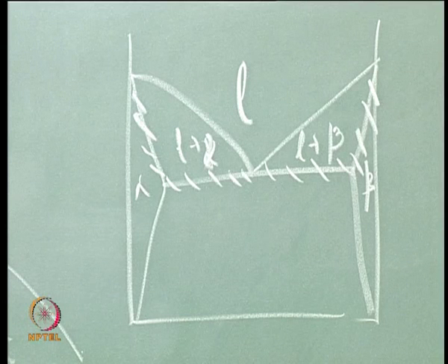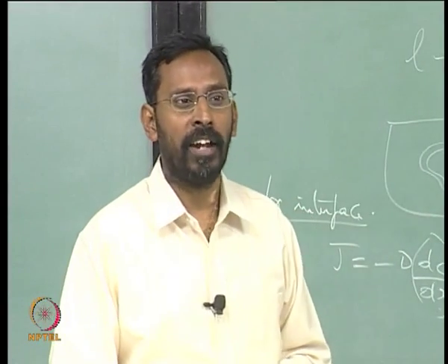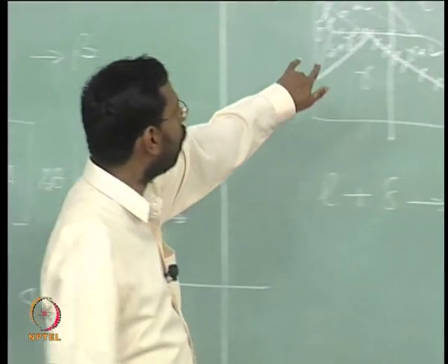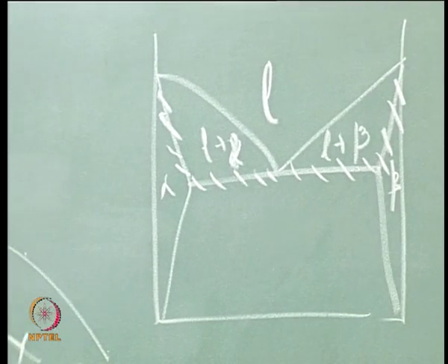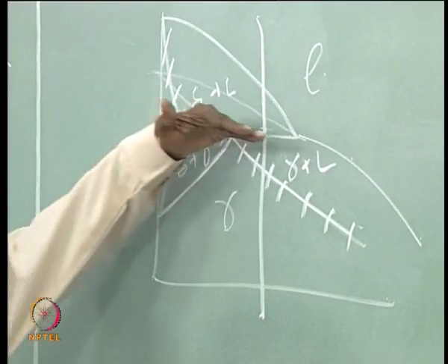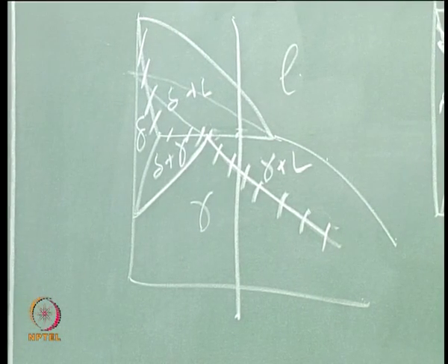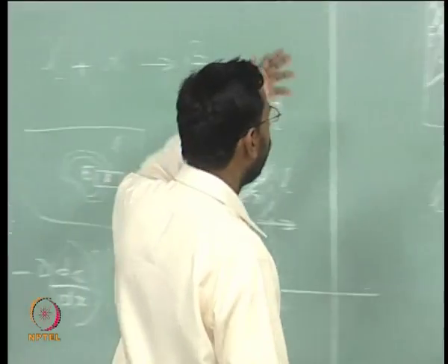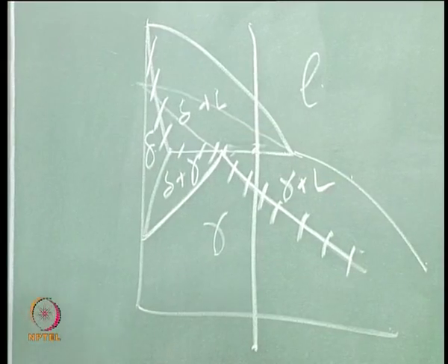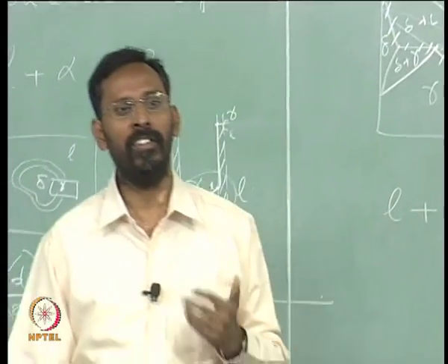In a eutectic phase diagram, the whole eutectic horizontal becomes a part of the solidus, whereas in a peritectic only a part of the peritectic falls into the solidus and the remaining part does not, because below this line you still have the liquid left out. If some liquid is left out, then obviously it is not a solidus line, and liquidus line is easier, the top portion. Similarly, here also the liquidus is easier. The only confusion that comes always is with the solidus.